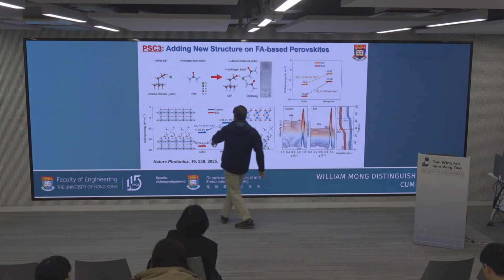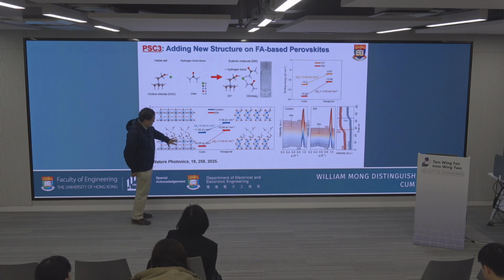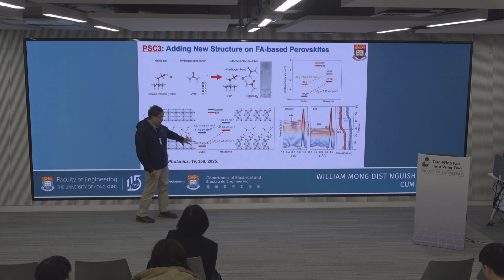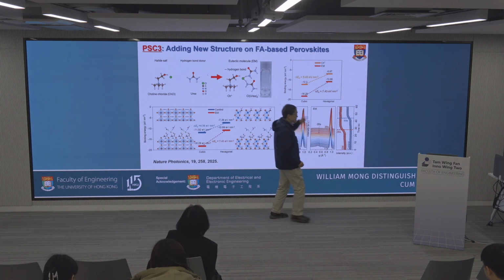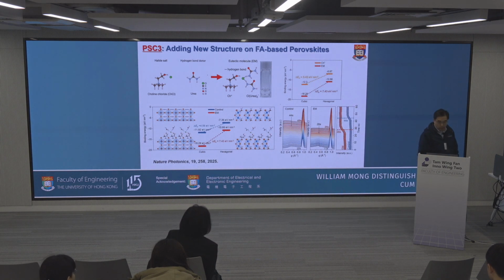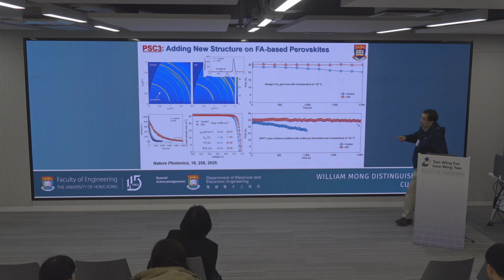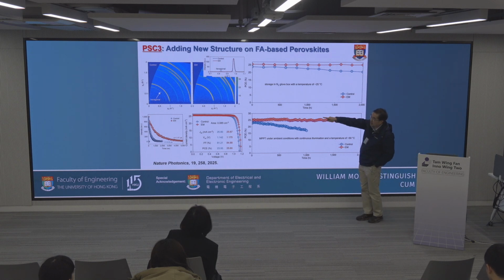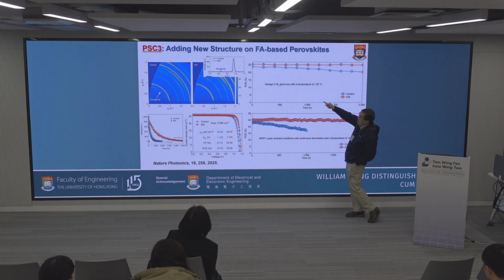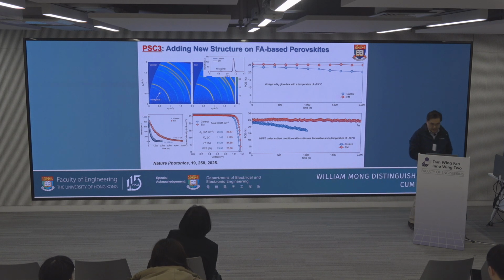That is what we find out: we finally favor the perovskite forming more uniformly in terms of phase. We have more cubic phase, so with that, hopefully we can work. Finally, this result shows that we suppress the hexagonal phase, which allows us to have more stable and higher performance devices.